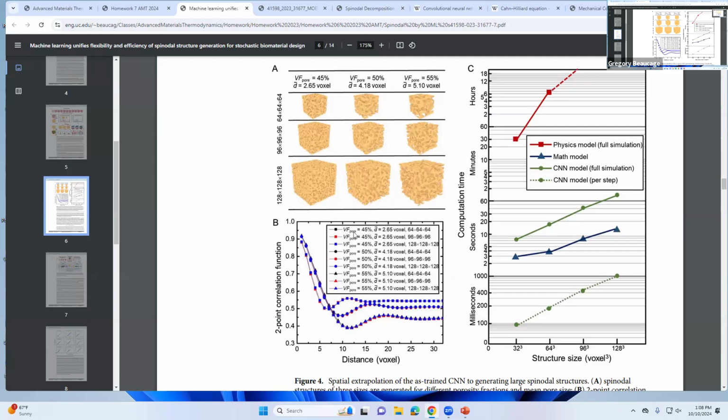So he's going like percent pores, which is 1 minus the density, or 100 minus the density. So the densest one is the lowest pore. So that's the squares. So the squares have the highest density, right? So this is reading that, so that agrees here, it's good. High density, lower density, 45, 50% density, and the last one's 45% density, that's the lowest. They don't go, this should be like the distance between the first and the second should be the same as the second and the third, and it isn't. So I don't know why that is. That's kind of an odd thing.